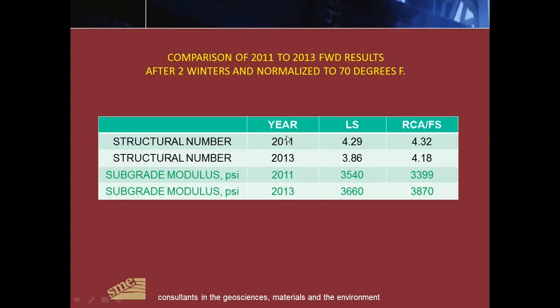Just in summary, the structural numbers between 2011 and 2013, this is the averaging of both lanes together. You can see that in 2011 the structural numbers were very similar, that over a 2 winter cycle there was a slight decrease in the structural number, but our limestone section really decreased more than what our recycled concrete foundry sand aggregate did.